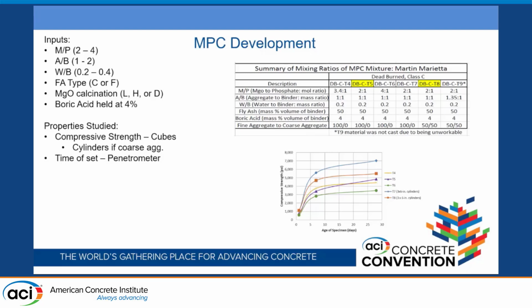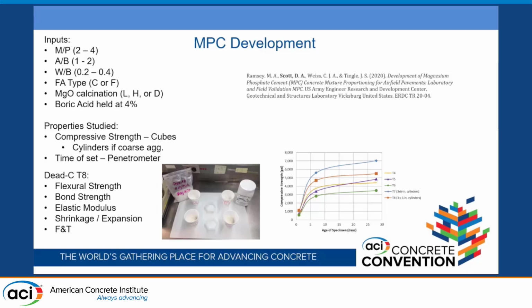Here's our strength results for those. And then in 28 days, we were getting 7,000 PSI. Which is pretty good. And just real quick offhand, in airfield specs, you have to have 5,000 PSI compressive strength, and then they also want a 650 flex strength at 90 days. So dead CT8 is the one that we went through. We did more in-depth testing. We did flexural strength, bond strength, modulus, shrinkage expansion, and then also freeze thaw. And then there's the citation for all of this non-proprietary MPC development work here as well.